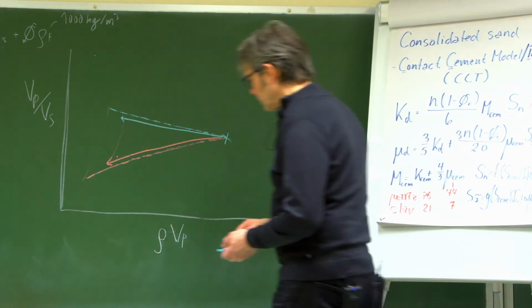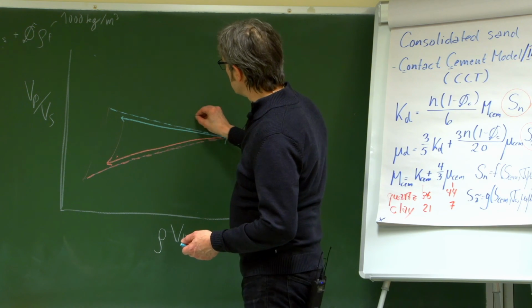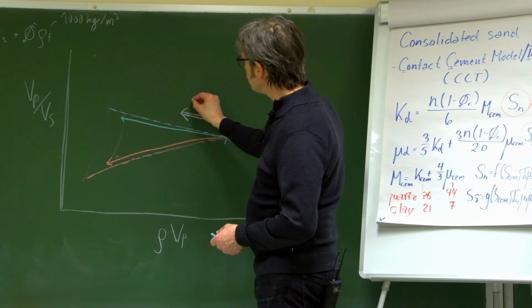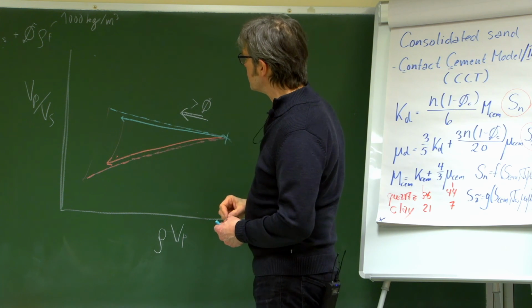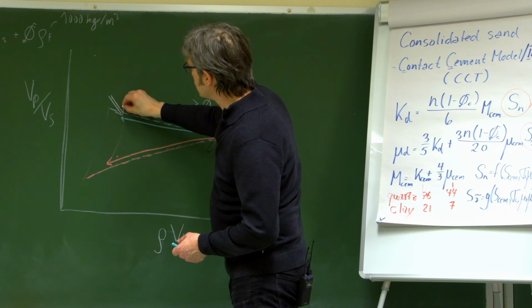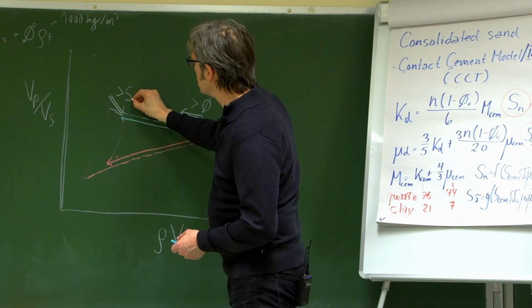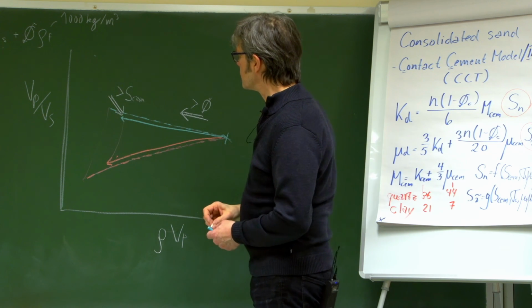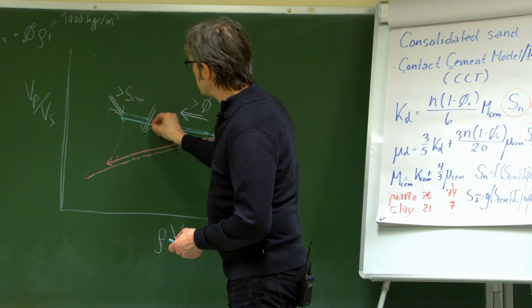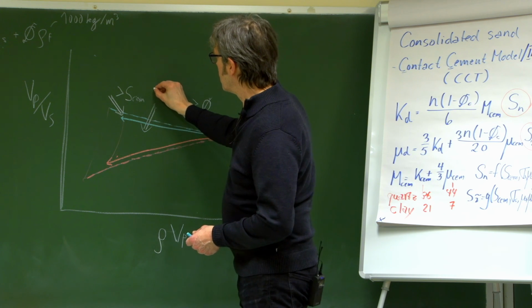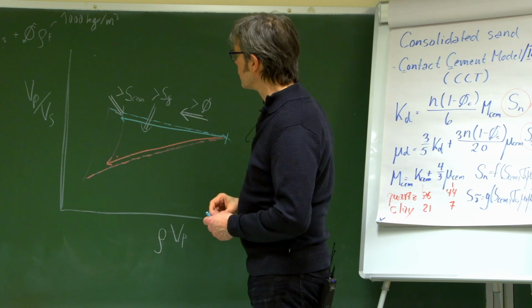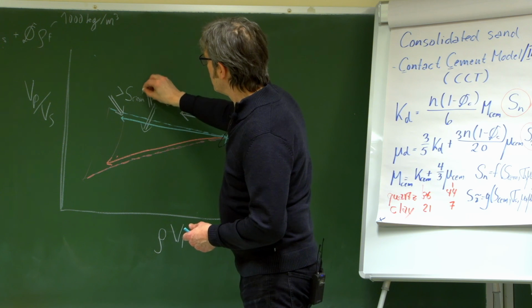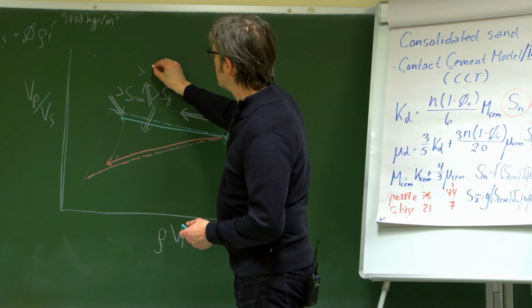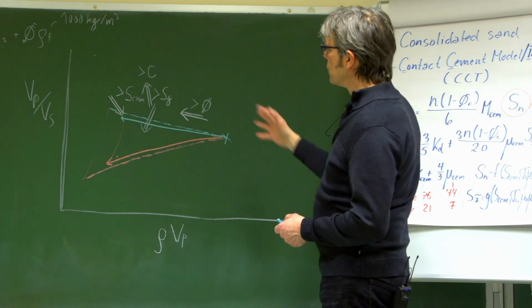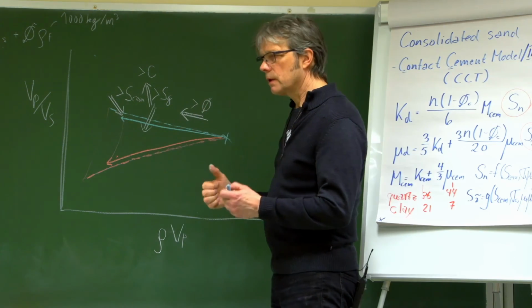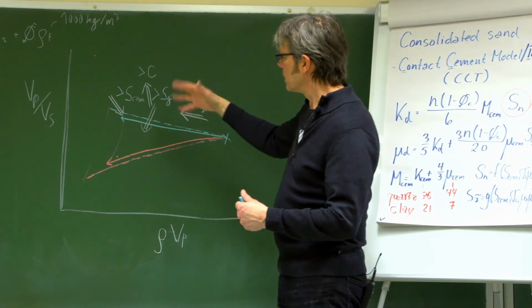So altogether, if we just summarize once more, we have a porosity effect. Increasing porosity would move a point in that direction. If we are increasing the cement or consolidation, we are moving in that direction. If we are increasing the hydrocarbon content, you increase the gas saturation, we are moving in that direction. If we are increasing the clay content, we're moving in that direction. So now we see we have some kind of rules of thumb. They're not orthogonal effects, but there are just some arrows here.